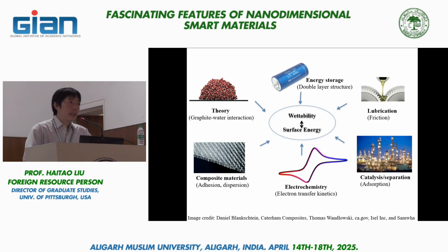So wettability is a very fundamental surface property. It's very simple to measure. I'm going to talk about the measurement in a sec. But it's also very fundamental in the sense that it's directly connected to surface energy, which is a fundamental property of all materials. If you think about the ways we use materials, actually the ways we use a lot of 2D materials, carbon materials, their application has a lot to do with surfaces. For example, in energy storage, in electrochemistry, there's always this interfacial arrangement of charged species, and how the surface interacts with the species. A lot of it comes from the surface energy.